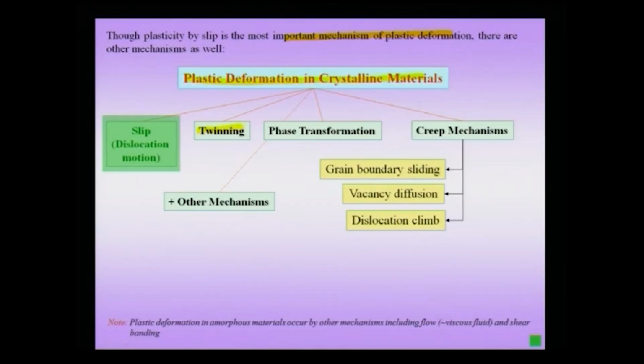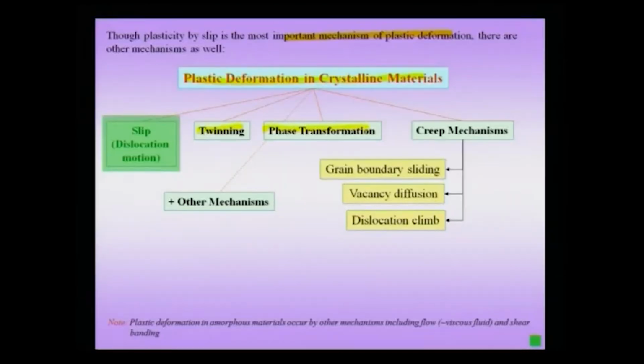Additional mechanisms could be phase transformation, and here when I am talking about plastic deformation, I am implying that there is permanent deformation in the material. That means, even in the absence of the load, there is a deformation which has been caused, which is going to be permanent, and therefore, phase transformations can lead to permanent deformation in the shape of a material. There are creep mechanisms like grain boundary sliding, vacancy diffusion and dislocation climb, and there are other mechanisms as well, which can give rise to permanent or plastic deformation in a material.